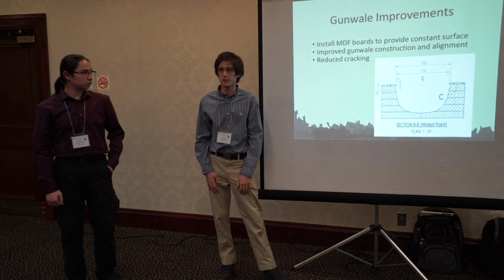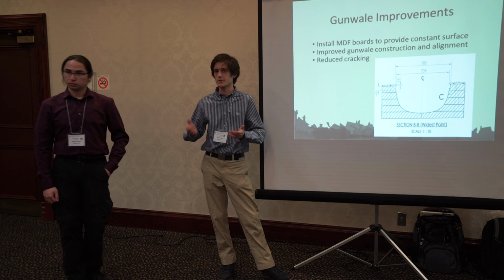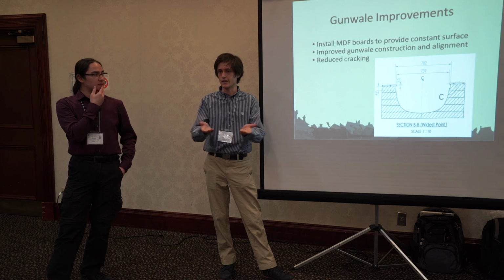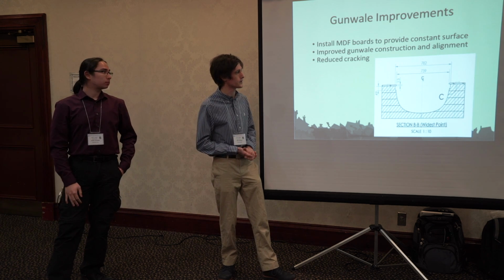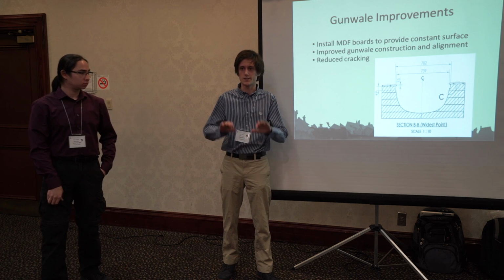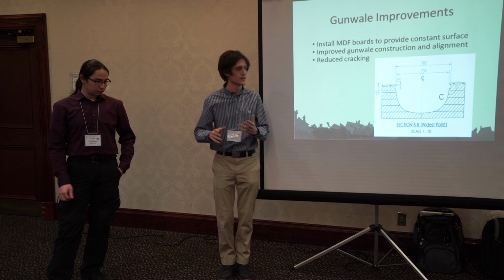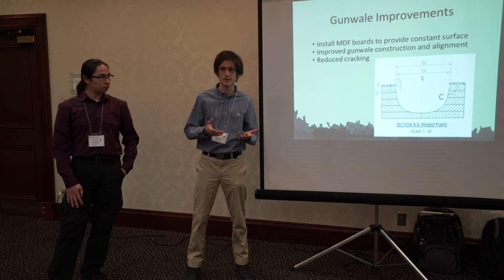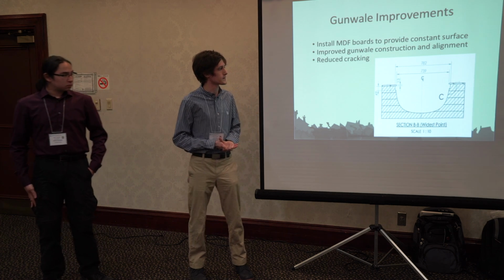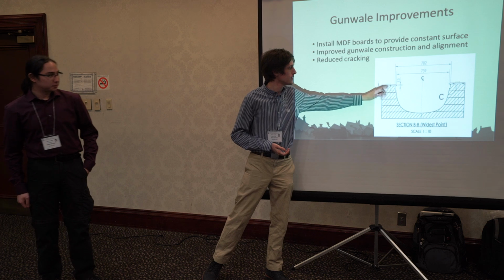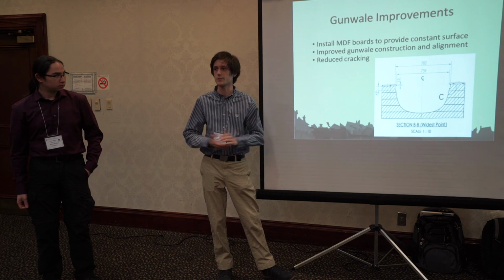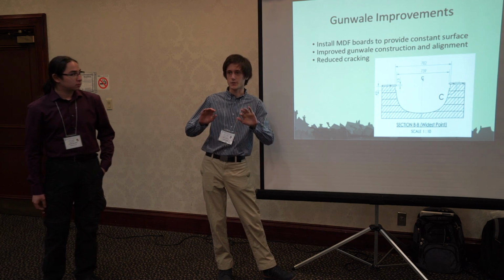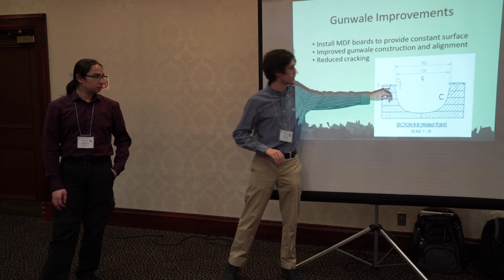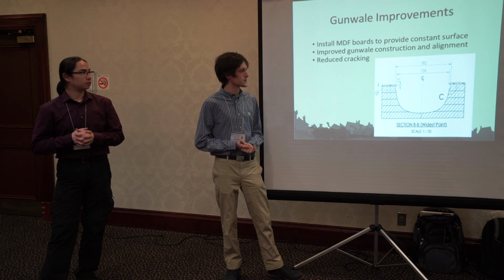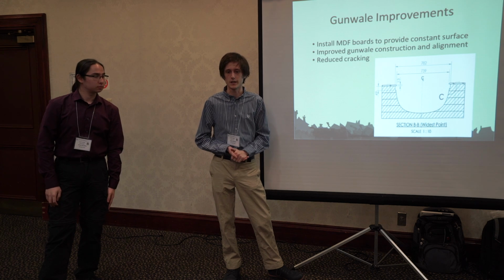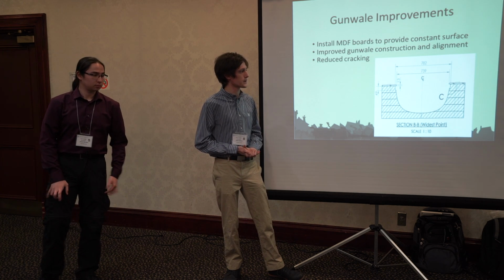On top of that, switching to the female mold caused a couple of problems with the gunnels. Previously, as we were making them, we could easily pat it in underneath the mold, and it'd have a flat surface of the table to keep it consistent going throughout the canoe. One of the problems with the female mold is that as you pat it up, the gunnels droop in to the middle, and it messes up the structural support that you calculate from the programs. So in order to fix this, James came up with the idea of putting MDF boards around the top. It's just a thin piece of wood that we wrapped with tape to stop it from sticking. As we're casting the canoe, we can pat on the concrete, and we have a place to build it up to. It keeps the lining consistent, it keeps us aware of how much concrete we're putting on, and it reduced cracking as the canoe was drying.